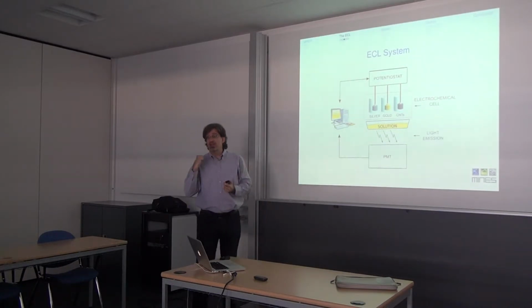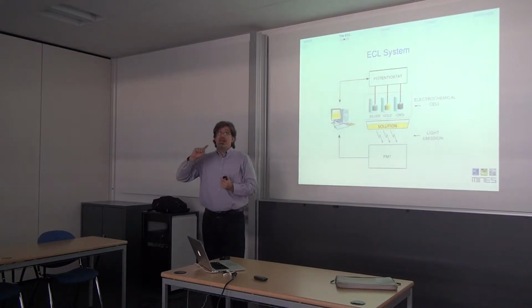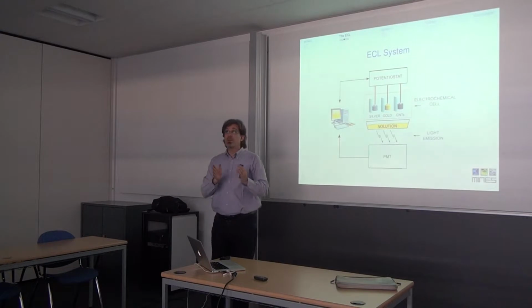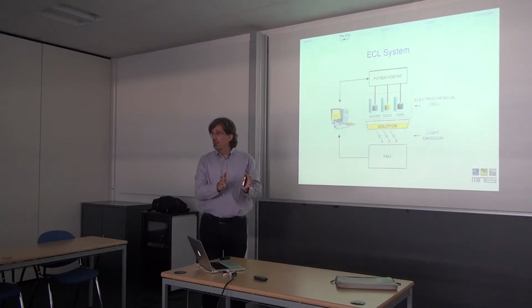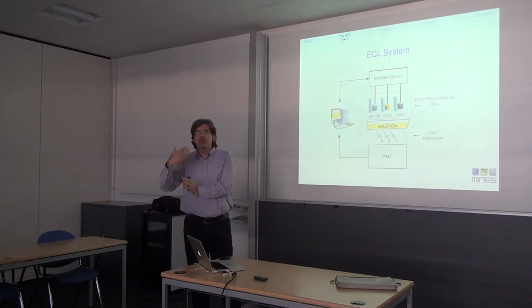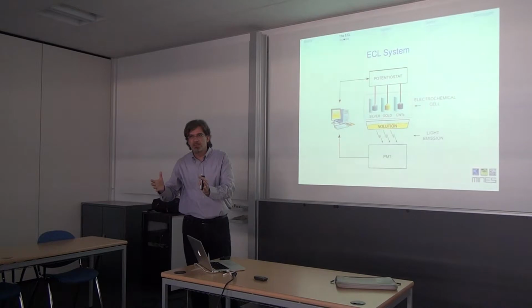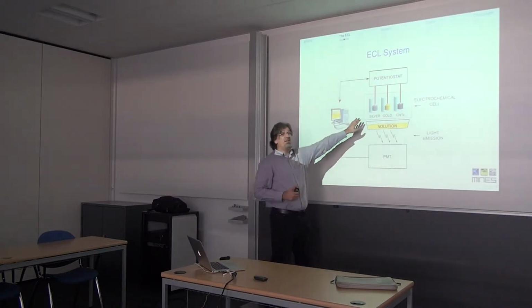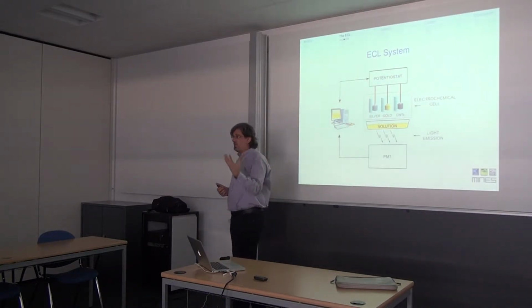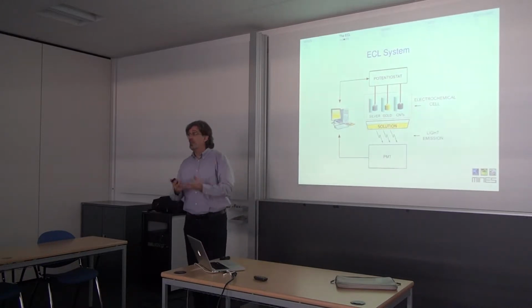So we decided to use silver for our reference electrode, because on one side it is not the standard, you do not have emission at the standard voltages you expect, but I will show you that it's not so important for us to have emission in a standard way. But using silver, you can imagine, we can integrate the electrode very easily.